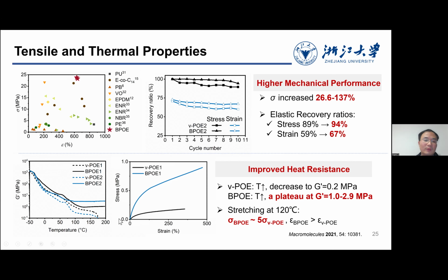For example, once the temperature goes to more than 150, this kind of cross-linked polymer still has a storage modulus around 1.0 to 2.9 megapascal, and you can see the plateau here. And if you're doing the stretching at a high temperature, 120 degrees C, they still show strengths 5 times those without cross-linking.